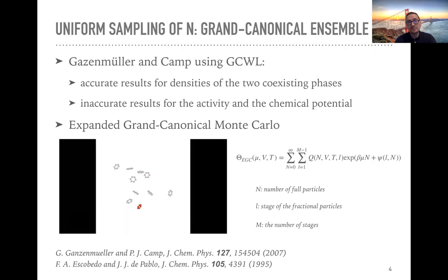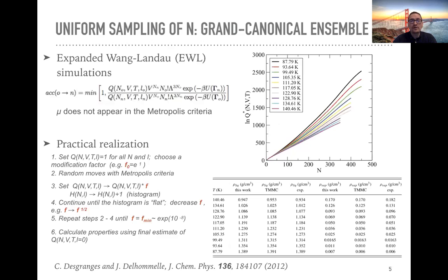What we're going to do in this case, and that's the expanded part of the name of the method, is use an expanded ensemble formalism. Essentially, what we see here is that particles that we are going to adsorb in the system are going to gradually shrink or grow, and this is going to allow us to sample and determine with accuracy what happens when the system becomes very dense, whether it's a dense liquid or a dense adsorbed phase. We've seen that it's extremely important for the accuracy of the partition functions that we determine. So this method overall results in this expanded Wang-Landau approach.